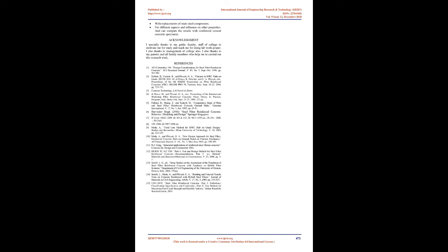Conclusions. Based on the results and observations of the investigation presented in this research, the following conclusions can be drawn. 1. The major parameters of concrete structures, like compressive and tensile strength, can be improved. 2. Innovative structures in different parts of the world have clearly indicated the unique, unmatched properties of this material and therefore the vast potential waiting to be explored. 3. The load carrying capacity is observed to be improved when a small amount, like 0.3% by weight of concrete, is added. 4. Overall it is advantageous to use 0.3% of steel fibers, which gives adequate results in all conducted tests for concrete grade M20 without making lumps or bunches of fibers.